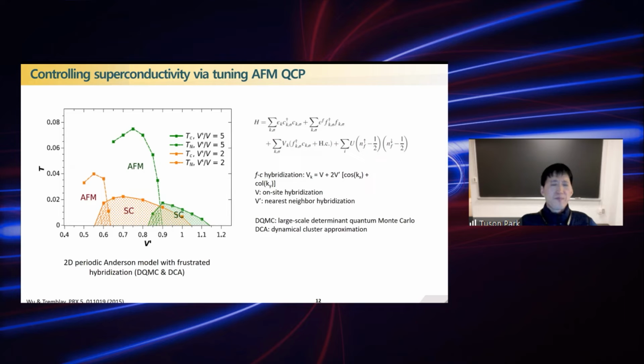This is the temperature and control parameter phase diagram by Wu and Tremblay, based on a 2D periodic Anderson model with frustrated hybridization. Here, V is the on-site hybridization, and V' is the nearest neighbor hybridization. When you change the ratio between the on-site and the nearest neighbor hybridization strengths, you can change the antiferromagnetic critical point, and the superconductivity arising from these critical fluctuations moves together with the AFM QCP, providing a way to tune the superconductivity by controlling the AFM QCP.